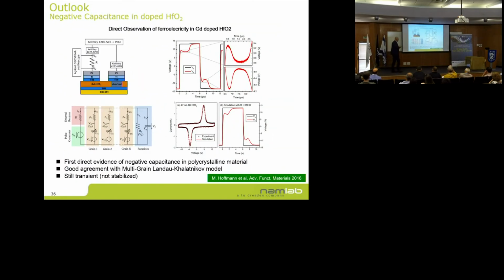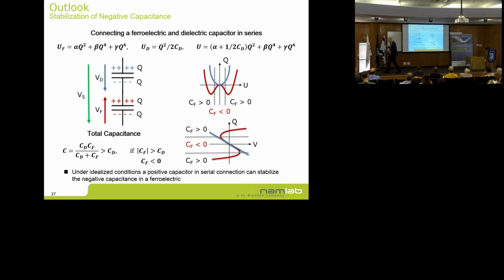And the first thing we try to find out is, can we see it in our hafnium oxide? So we did a measurement with a series resistance, and if there is a negative capacitance, we should see at some point in time that the voltage is not going up continuously like in a normal capacitor, but it should come down. And we really see that. So there is indication of negative capacitance. First step, because it's still transient, it's not stable, it's not useful for what I have shown, but I think it's an important result because you cannot be sure that you really have that in a multi-domain, multi-crystalline structure. Maybe in a single crystal, it's pretty obvious that you will see it, but the problem is the multi-domain structure.